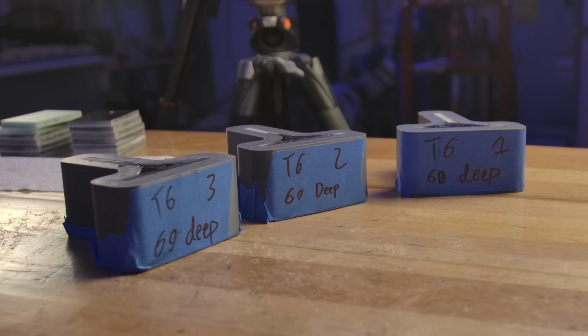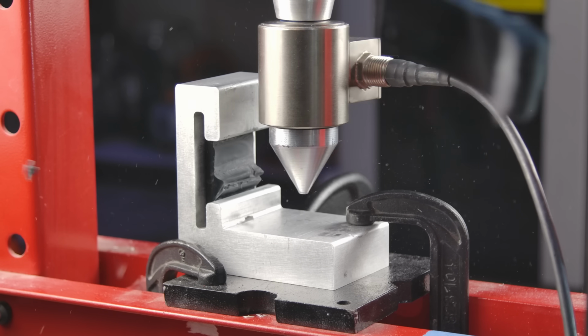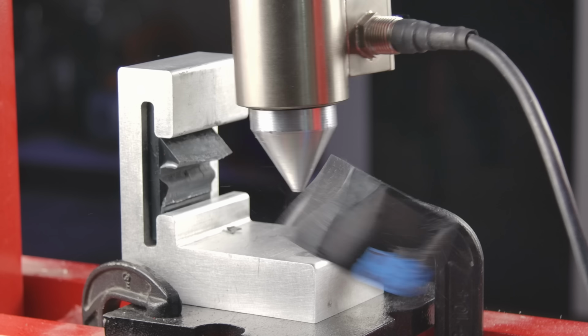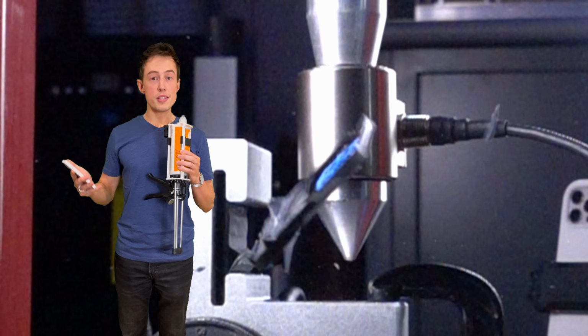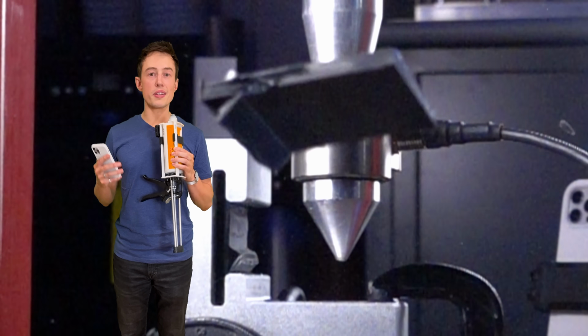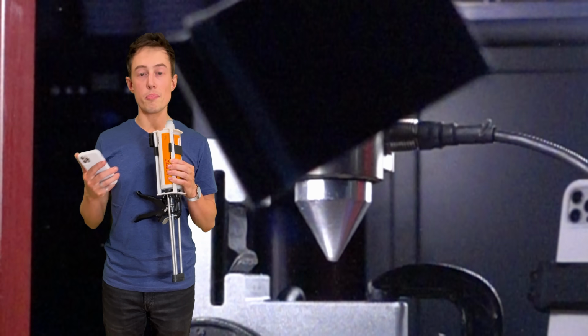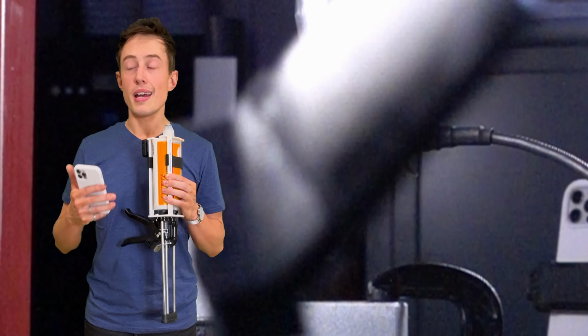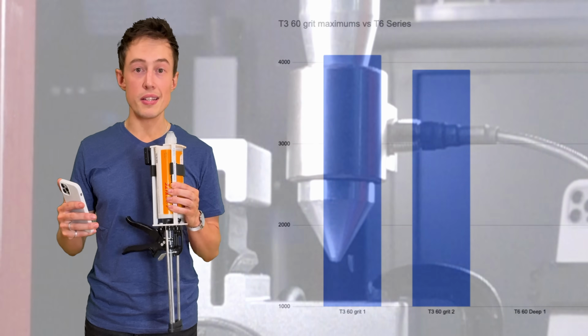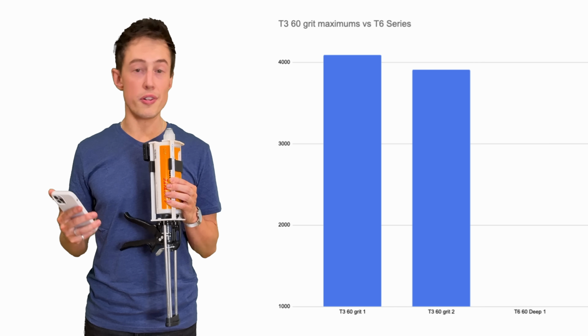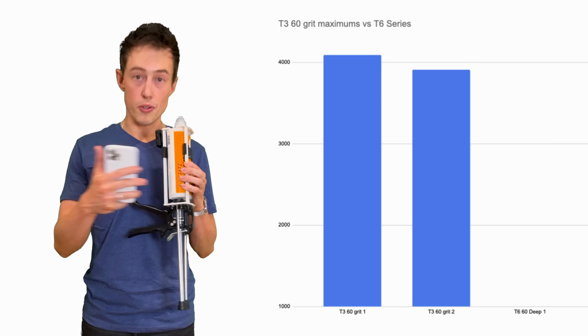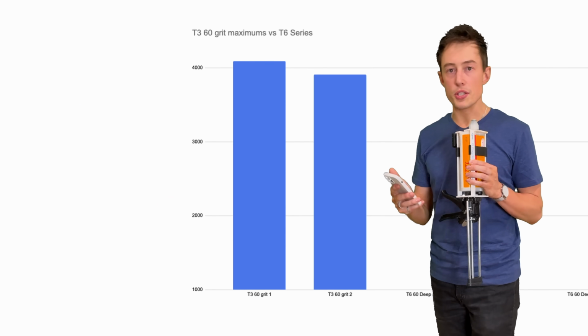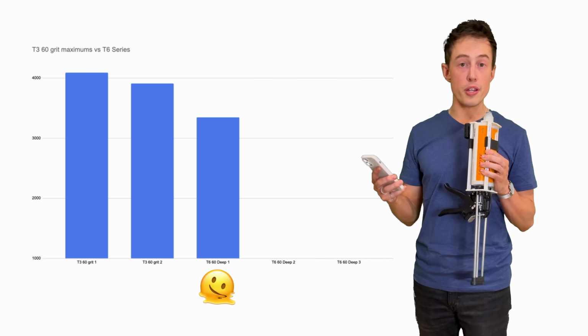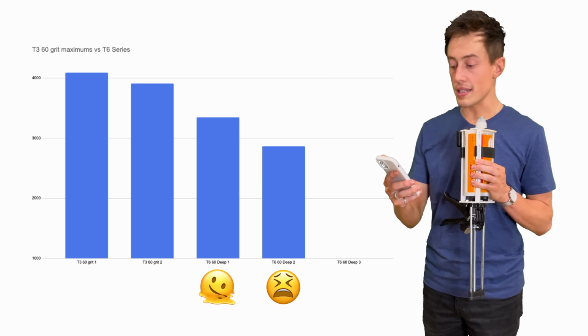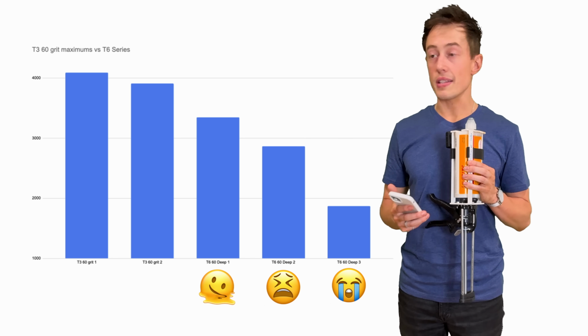So let's fast forward and break these samples. These 3 samples are all identical with consistent preparation, cleaning, epoxy, degassing, etc. And yet the only thing we are consistently doing is falling well short of that 4,000 Newton number from the early 60-grit tests. And the spread between them is wide. With 3,300, 2,900, and 1,900 Newton breakpoints, this is not good.